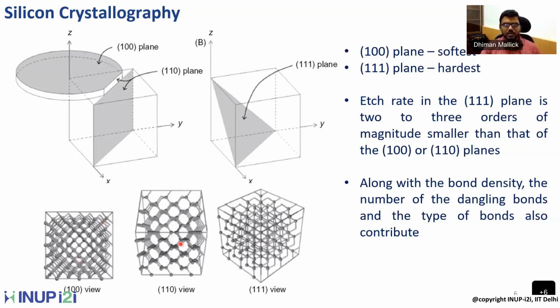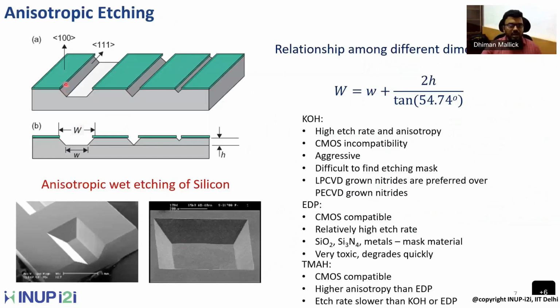Now, this creates a mismatch of etch rate in the different planes. When you start etching silicon, your 100 plane, which is the top surface plane, etches very quickly. And when the etching continues and comes down to this 111 plane particularly, the etching rate is minimized. It becomes very small, so at that time the etching kind of stops. Ultimately, you get an etching profile like this. This is again a 100 plane. When you are doing wet etching from the top surface, ultimately when it comes to this 111 plane the etching stops, and so you get a tapered profile due to the etching.